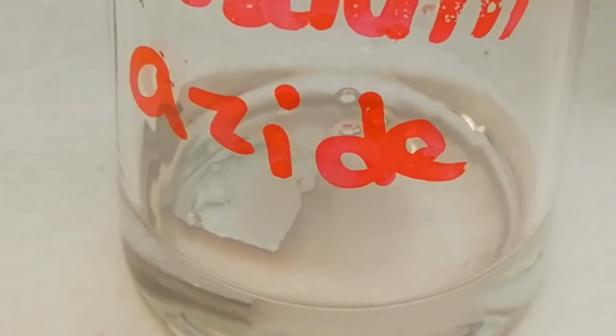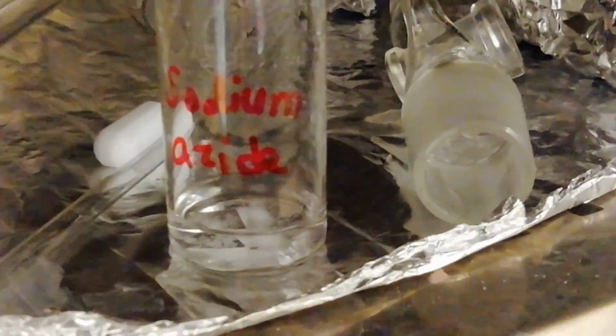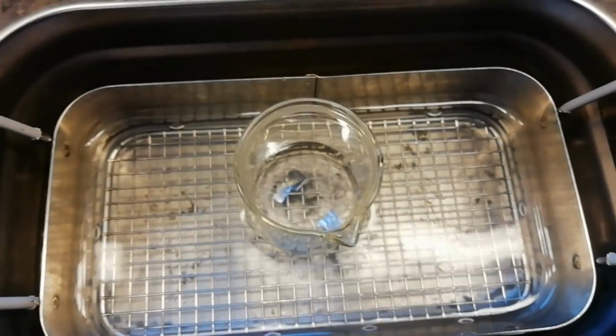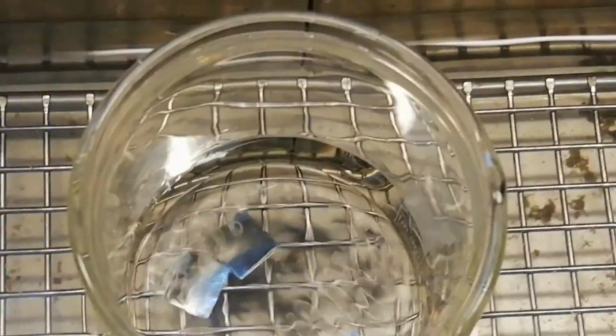Observation: sodium azide is not completely soluble in DMF solvent. Only after heating it is soluble. Again, the surface and reaction mixture is heated in the 60°C oven. The azide modified substrates are rinsed, sonicated in DMF 5 minutes, ethanol 5 minutes, and dichloromethane 5 minutes, and dried in nitrogen or argon flow.